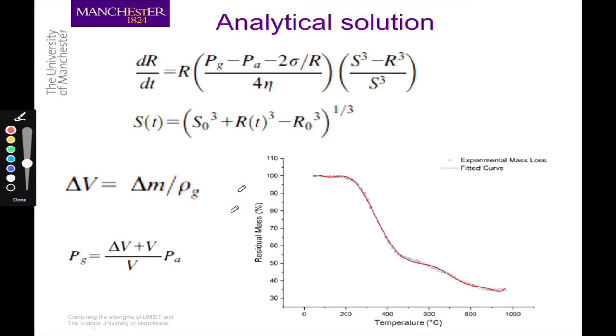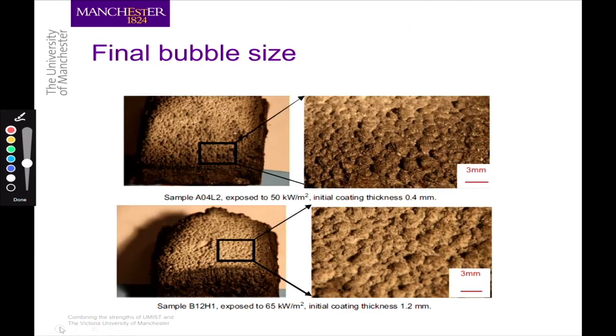Of course, to do that, we need to calculate the pressure, but pressure simply comes from the decomposition of solid intumescent coating into gas, because solid intumescent coating is about 1,000 times denser than gas. So with that, we can calculate the pressure. And of course, it is possible to measure the surface tension and the viscosity of the material. So that is what we've done, and we have implemented this in our research.